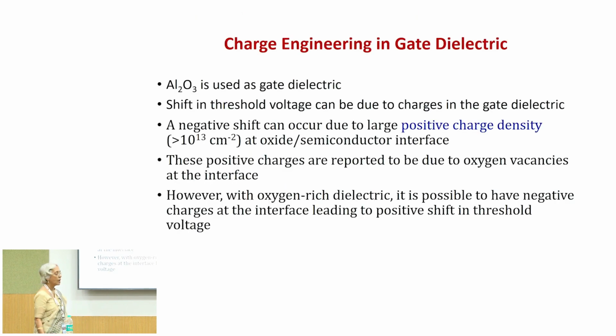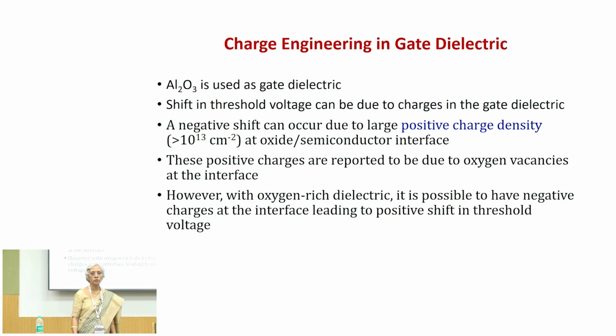As I said, we have also tried to do charge engineering in gate dielectric, and for this the gate dielectric that we have used is aluminum oxide. Now, I already mentioned that shift in the threshold voltage could be due to charges in the gate oxide. There can be a negative shift if you have positive charges in the gate oxide. By the same logic, it is possible to have negative charges at the interface, and it can lead to positive shift in the threshold voltage.